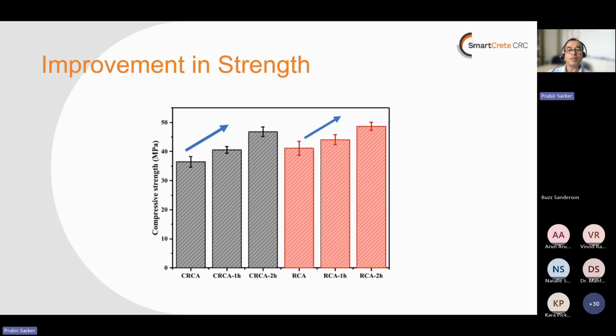And the improvement in strength also was observed in the concrete made by using the aggregate after carbonation. So concrete made by CRCA without carbonation, concrete made using 1 hour carbonation and 2 hour carbonation, and these are the concretes made with other recycled aggregate with 1 hour and 2 hour carbonation. So you can see in both cases there was an improvement of the compressive strength by using the recycled aggregate which went through 1 hour or 2 hour carbonation.